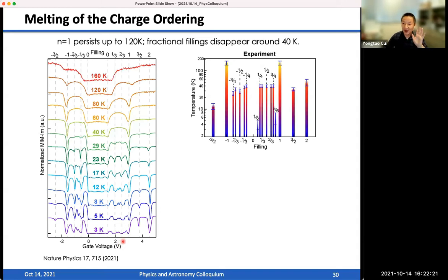There's one way to not measure the density but calculate it, assuming a parallel plate capacitor model. Using that, we can calculate the density in terms of the actual density we put on the Moiré lattice. Then, to calculate the fraction, we also need to know the size of the Moiré lattice, which we can measure using optical measurements to determine the alignment angle of the two lattices. From that, we can calculate the density. So that's one way to confirm the density.